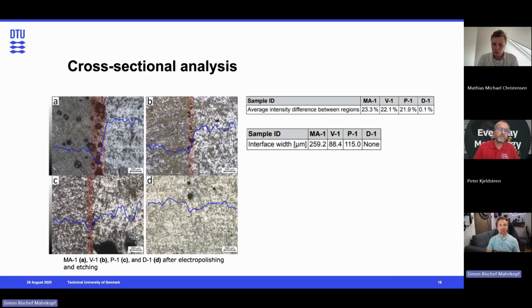Yeah. And what's interesting is you can actually see in sample A that the martensitic part was printed first, and then the other part, the austenitic, afterwards. And the porosities are in the martensitic part here. And you can actually see all these porosities are from the initial edge effects. And when then trying to create the second print afterwards, you didn't get the porosities, but you have a lot here in the interface, which are the critical areas. Exactly. And with A being the conventionally sliced part.